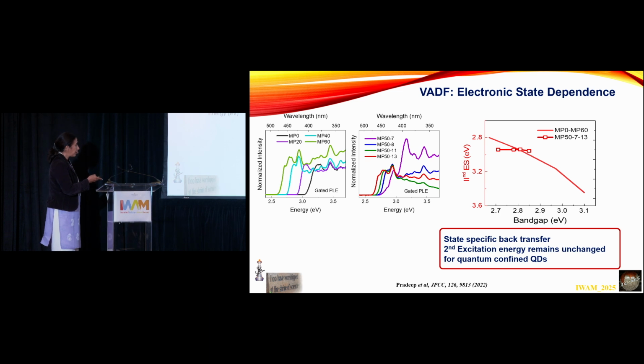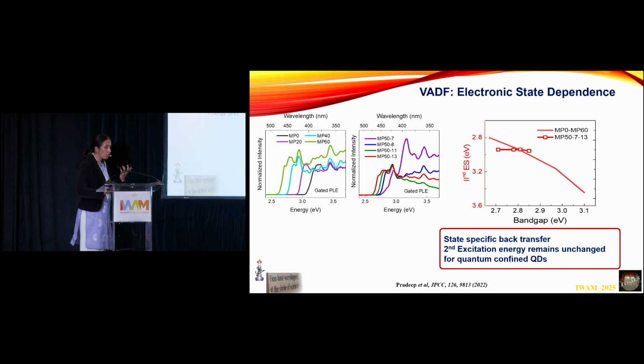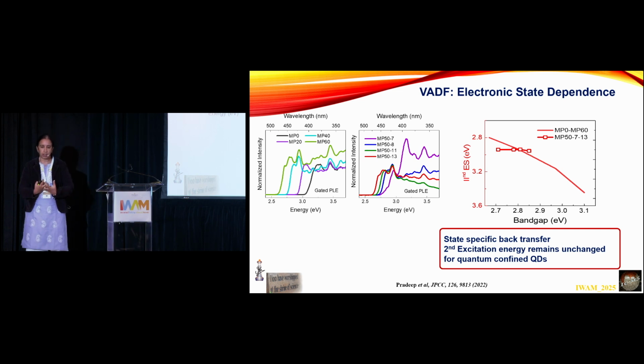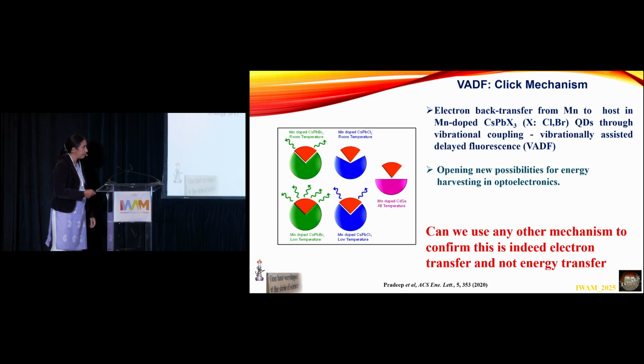And to our surprise, we see that for the composition variation, not just the first excited state, but all the second, third, fourth change. But when I have size variation, the first excited state does change, but the second, third, fourth are more or less at the same position. And since my VADF is not changing as a function of size, we believe that the higher excited states are responsible for coupling this manganese with the host and not the lowest excited states.